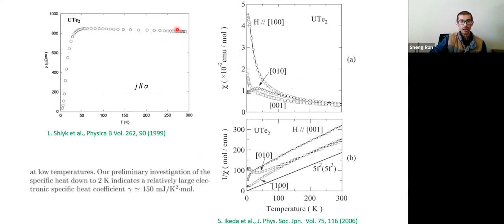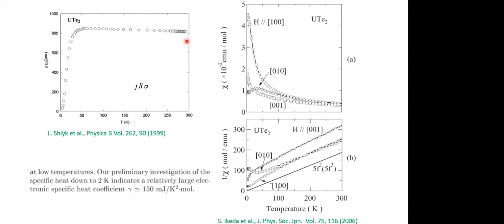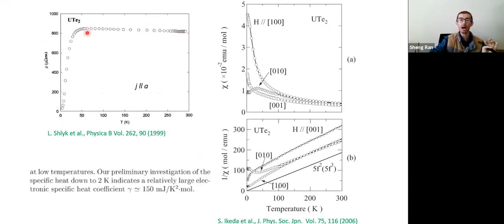Okay, here is resistance as a function of temperature. You can see this is a very standard uranium heavy fermion compound. At a high temperature, resistance slightly goes up due to the single-ion Kondo effect. And at the lower temperature, there's Kondo coherence. Therefore, the scattering becomes coherent, and resistance drops.